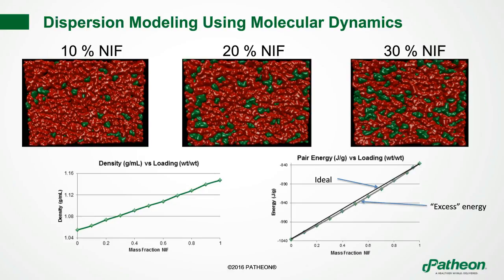So there's two things that are happening here. One is that the nature of the drug and the nature of the polymer is going to be one of the determining factors in whether you see agglomeration. But the other is, of course, how much drug is there. So when you have a large amount of drug, say 30%, which is actually starting to become a fairly large amount of drug in the system by weight, you actually start to see agglomeration. And we see this with a lot of drugs. This is why a lot of dispersions really can't push beyond 30 to 40% loading.